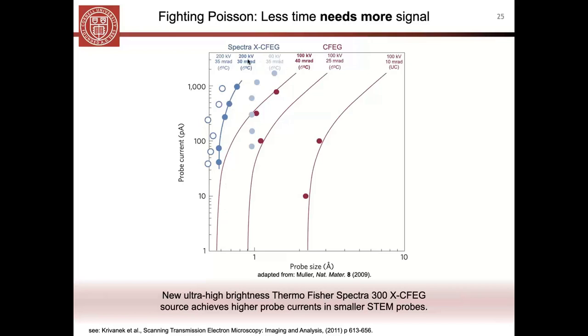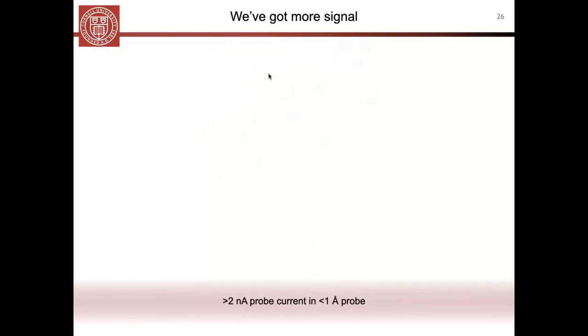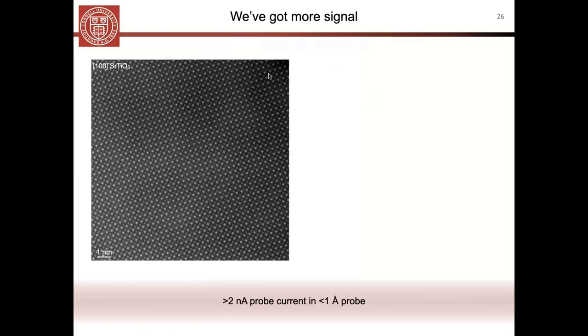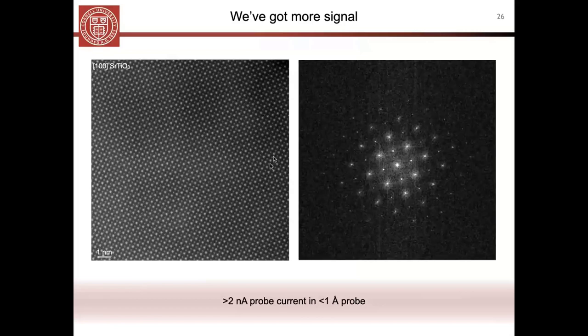And so, of course, this is a function of voltage and apertures and all these other things, but really the takeaway from this plot is that what we're moving towards with this new source is putting a lot of current in a very small probe. And so the clearest way to see that is just to do it. Here's an image of strontium titanate with more than 2 nanoamps of probe current. Again, for people who maybe are less familiar with STEM, that's a lot of probe current.